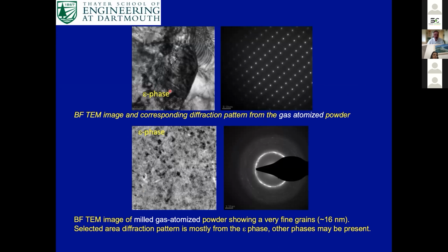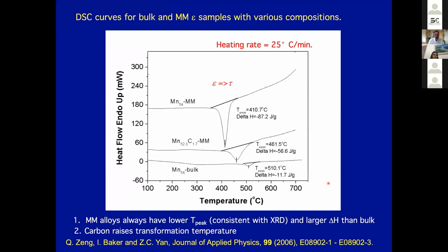These are transmission electron micrographs. So this is before milling, when we've got the epsilon phase, and you can just see a diffraction pattern here from that. After mechanical milling, you've got this really fine microstructure, and the diffraction pattern shows a ring pattern because we've got numerous grains. And from X-ray diffraction, we ended up with a grain size of about 16 nanometers in this material.